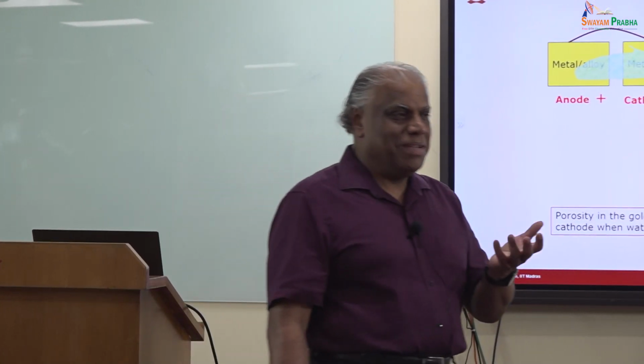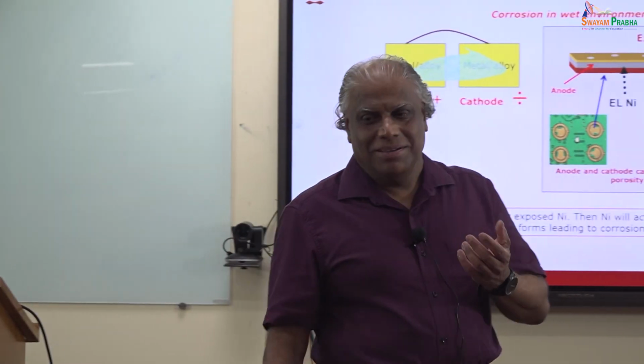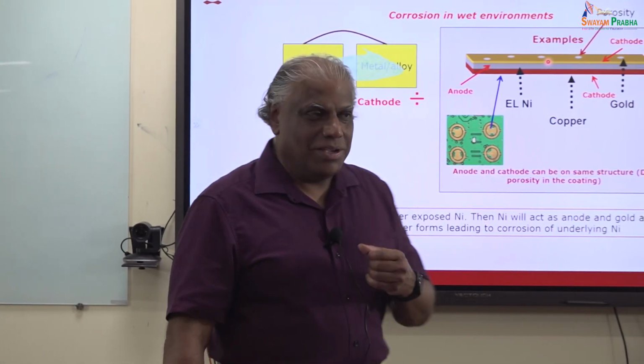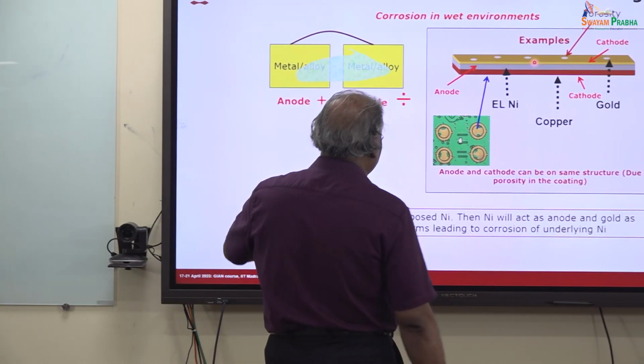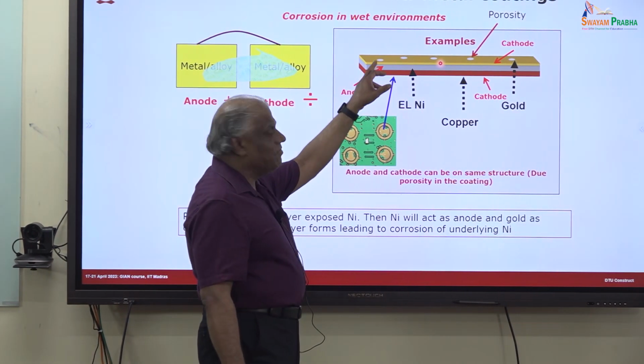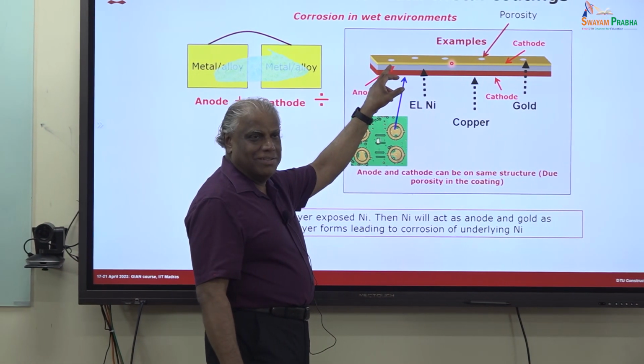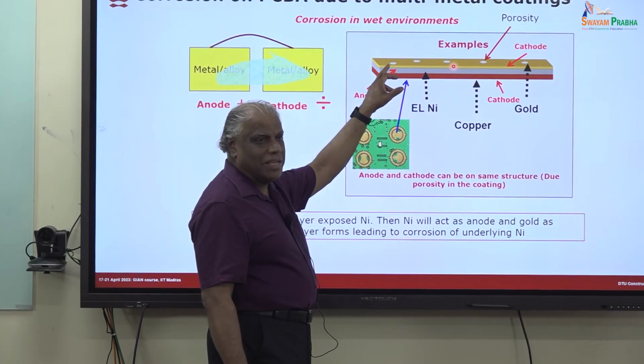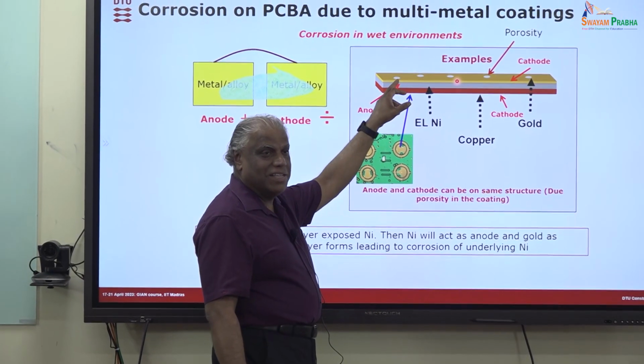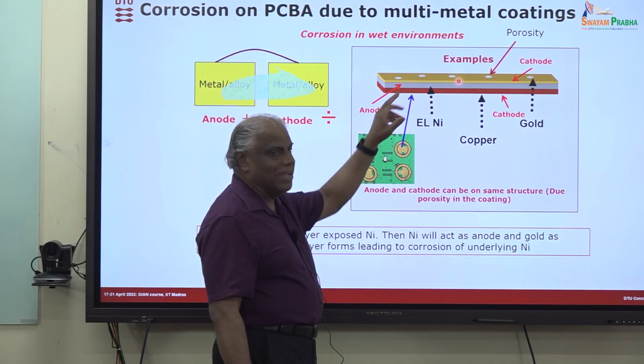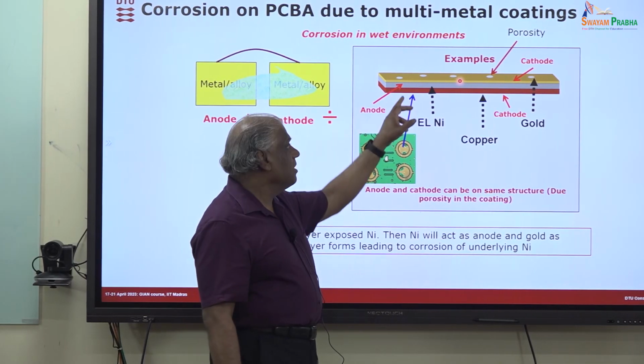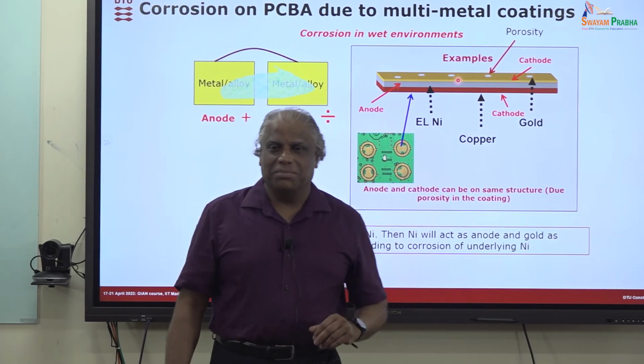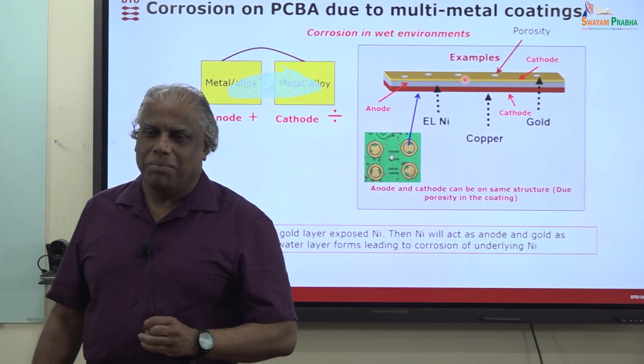Amount of copper. So that means that the copper is very soluble in gold. So if they put gold directly on the copper, there will be interdiffusion between copper and gold, and that means that so many different types of intermetallic particles and phases are going to form between gold and copper. So the diffusion barrier, this nickel, will act as a diffusion barrier between the copper and gold.